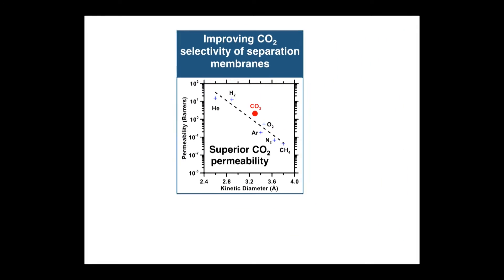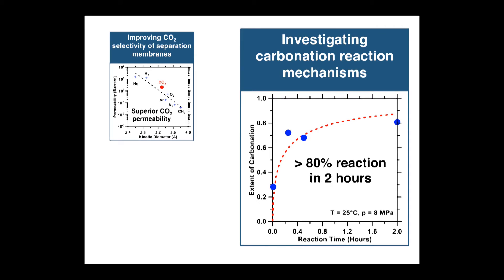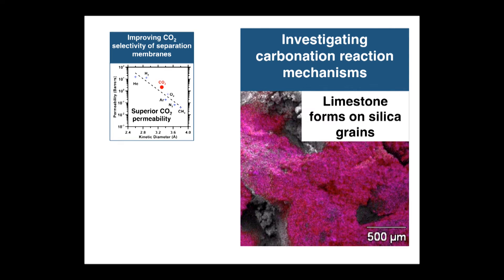Dr. Bu Wang and I have been focusing on investigating the actual mechanisms of the carbonation reaction by which CO2 is incorporated into limestone. We have found the reaction to be quite rapid, reaching over 80% completion within two hours, and we've also found that it can provide strength. This is an SEM image that shows limestone colored in pink based on its elemental analysis, and you can see that it's forming on silica grains in a cohesive layer, which could provide strength in binding aggregates the way normal cement does in concrete.